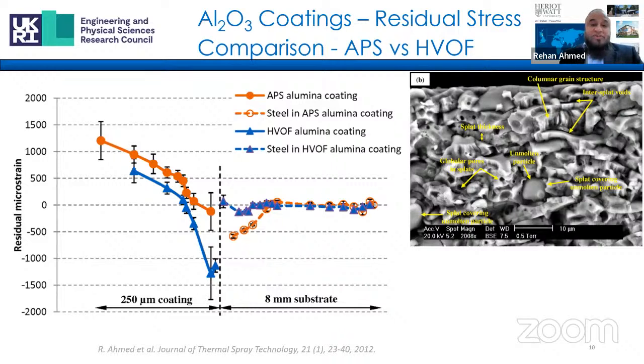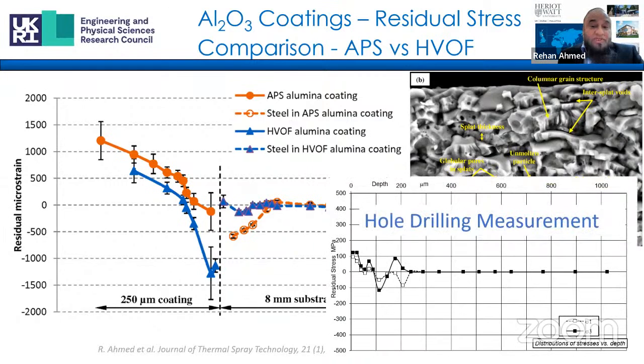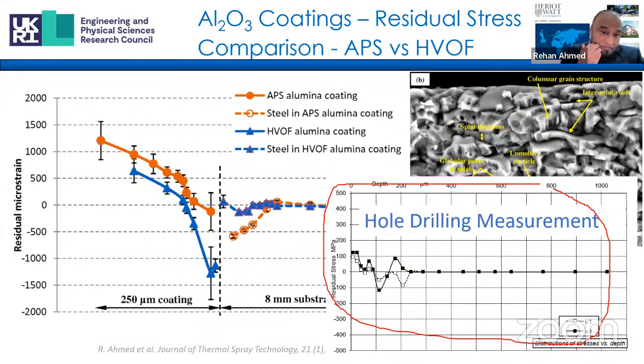And as these coatings are brittle, aluminum oxide is quite brittle material, and have a complex microstructure, it is not always possible to get a reliable measurement using the destructive or semi-destructive techniques such as the hole drilling, where the coating can crack. So this is shown by the insert here, where the residual stress profile measured by the hole drilling technique becomes unreliable. So care needs to be taken when selecting measurement technique in thermal spray coatings, as not all the techniques can be applied to all materials.